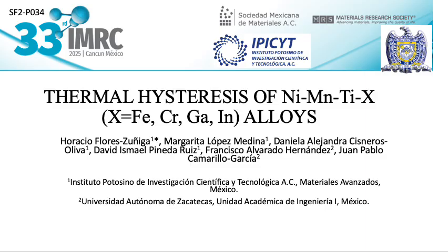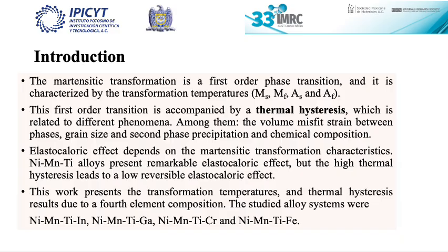Our work is thermal hysteresis on nickel manganese titanium X alloys, where X means the fourth element addition of iron, chromium, gallium, or indium. The martensitic transformation is a first-order phase transition, and is characterized by the transformation temperatures MS, MF, AS, and AF. This first-order transition is accompanied by the thermal hysteresis, which is related to different phenomena. Among them, the volume misfit strain between phases, grain size, second phase precipitation, and chemical composition.